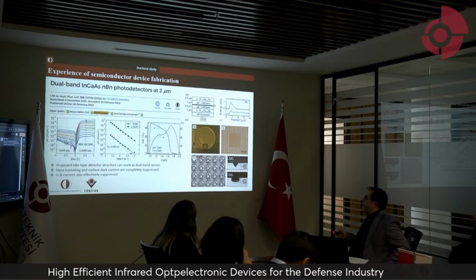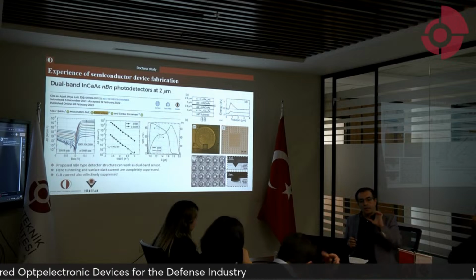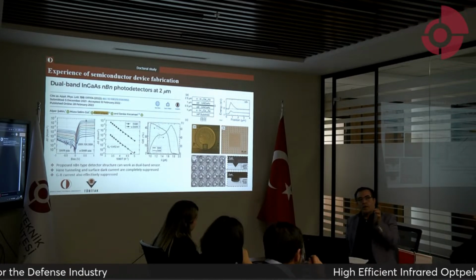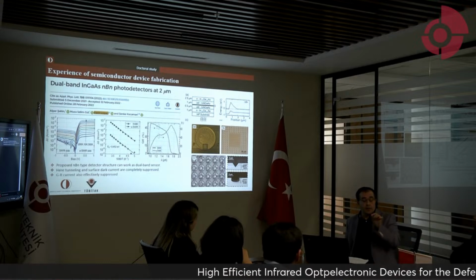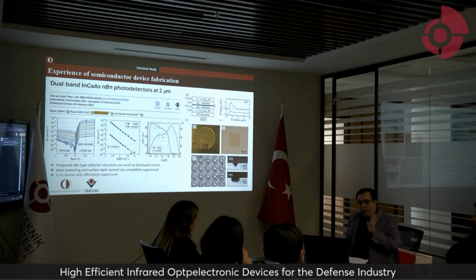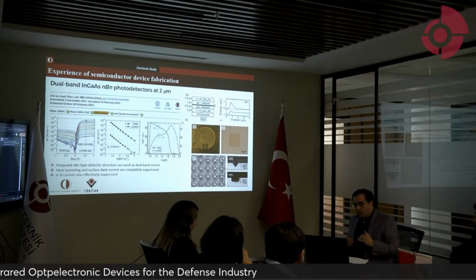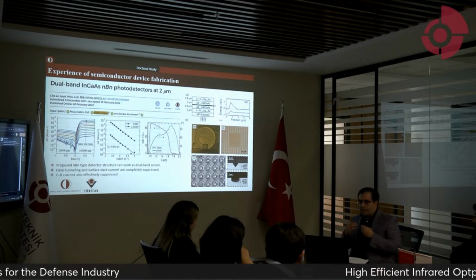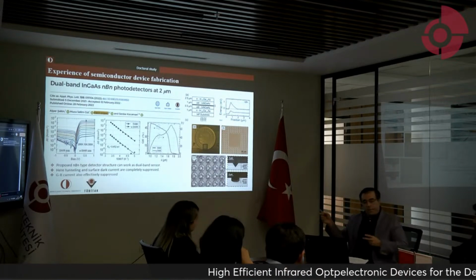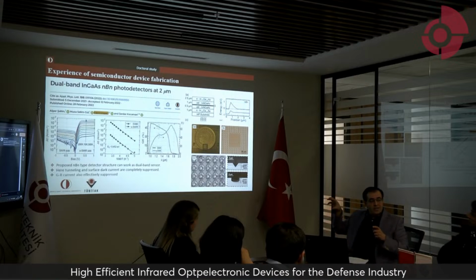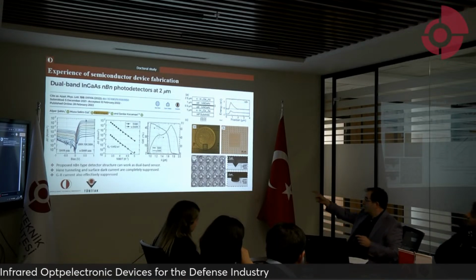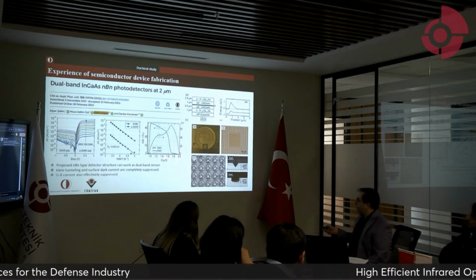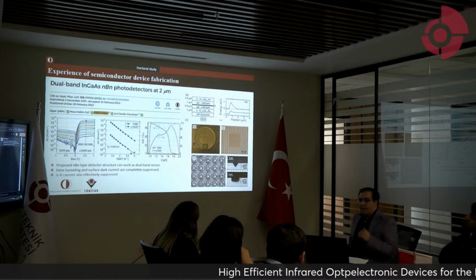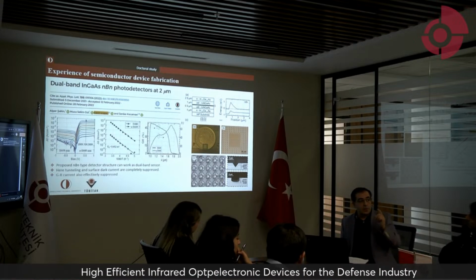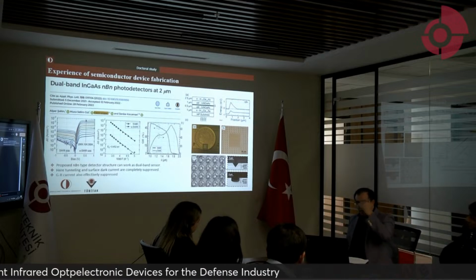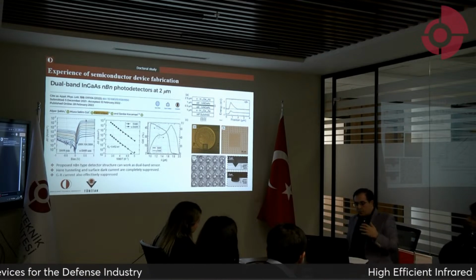Normally, indium gallium arsenide's natural band gap cutoff is 1.55 micrometers. But here we try to extend this wavelength. If you want to increase the wavelength, you can see the band gap. Actually, this is the beginning of our study. We can exceed this wavelength. We say wavelengths after 1.55 are extended short-wave infrared. If you want to see beyond cloud or dust, you need to increase the wavelength.